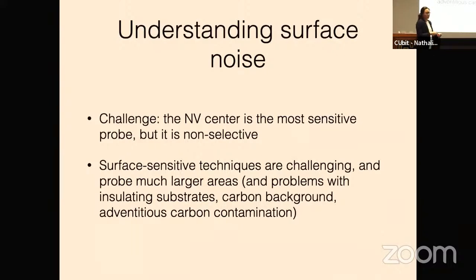There are a bunch of ways to do surface science, right? You can just look at the surface directly and try to learn things about that surface. In general, these techniques are quite challenging. There's a lot of technical problems when you look at carbon in particular, and diamond is very insulating, so that causes issues. But I would say that there's an even more fundamental problem, which is that a priori, you have no reason to expect that the surface spectroscopy is going to give you relevant information because the NV center is probing this very tiny area, right? It's basically just looking at its nanoscale environment, whereas the surface technique is looking at much, much larger areas with much lower sensitivity. So whether or not you're actually going to find anything that correlates appropriately with your NV center is sort of up for grabs.